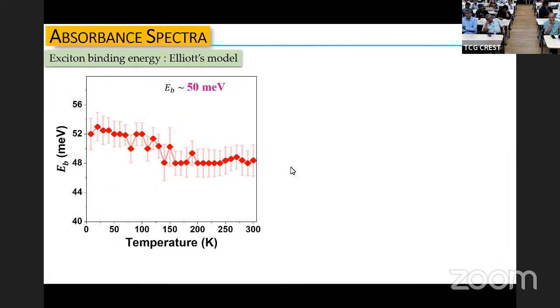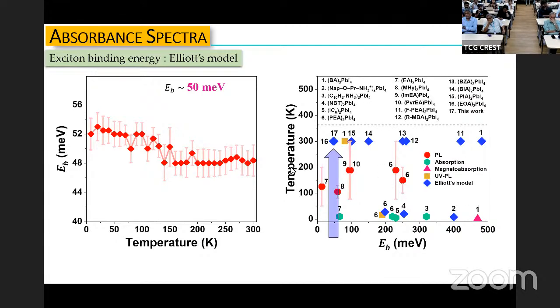Look at the excitonic binding energy. It's on the order of 48 millielectron volts, which is much, much smaller than the values I was showing you earlier, more than 100 millielectron volts. We compiled all reported literature data using absorption experiments, which are these blue dots at different temperatures, on this excitonic binding energy scale. Ours is the lowest excitonic binding energy of all these 2D materials. You'll find that this one seems to be lower, but this is photoluminescence. The same material with another technique comes to a higher binding energy, and that shows you the dependence on the technique. So if we stay with the absorption data, there's absolutely no doubt that it's the lowest excitonic binding energy that we have realized.